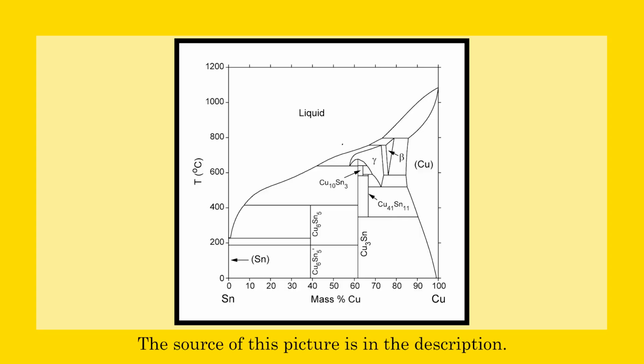Finally, we should check out the tin-copper phase diagram for two reasons. The European Union banned leaded solders for most cases in 2006, and solders became highly tin-rich. On the other hand, the solder has to create some kind of bond with the copper of the PCB. The diagram is more complicated than the previous one, but I must highlight these. These are the intermetallic compounds.